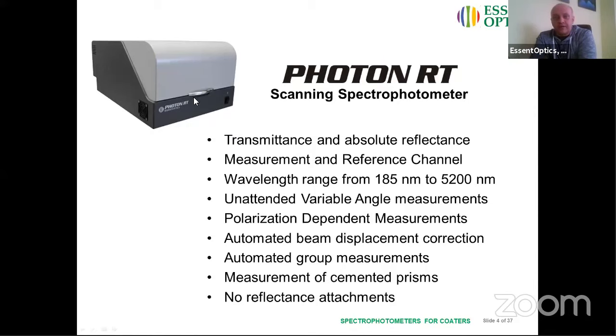Couple of key points regarding this instrument, which is used for flats, is that we can match the needs of customers from 185 nanometers in UV range up to 5.2 micron in infrared in a single system. And in the same system, we can do unattended variable angle measurements, polarization dependent measurements, automated beam displacement correction, group measurements, cemented prisms of different shapes, and we basically don't need any reflectance attachments for this.